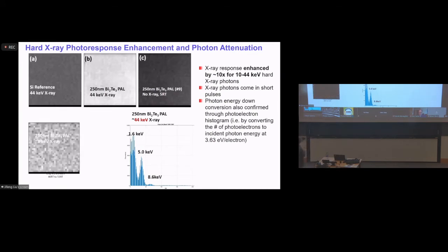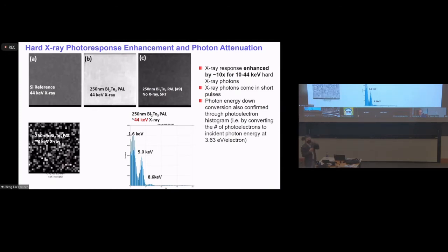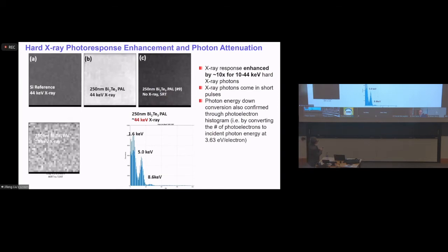Interestingly, this light X-ray source is triggered by the radioactive decay of americium. So you'll see the X-ray actually comes in pulses. These are a few frames captured here. When the pulses of X-ray come in, you can count the number of electrons received by each pixel, because you can convert the voltage signals read into the number of electrons, knowing the capacitance of each pixel. Then you can do a histogram to plot how many electrons you have collected. And using Caitlin's result, 3.6 electron volts per electron, you can back out the incident energy of the X-ray photon that you receive at the silicon pixel after the incident 44 keV passes through the pale layer.